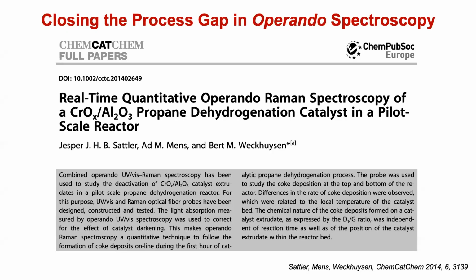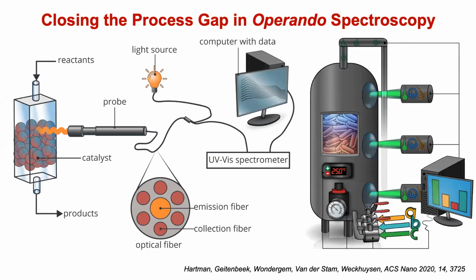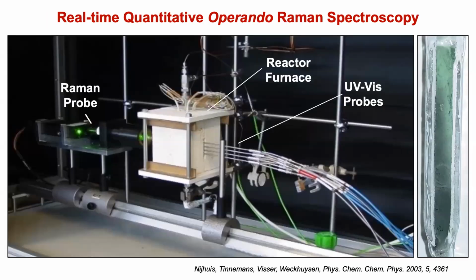This culminated in this paper, actually a ChemCatChem paper, where we published it, but it is a journey. It started first with a praying mantis cell, diffuse reflectance UV-vis, then optical fiber, on the left. And where we want to go is what is shown on the right, where we develop not only temperature sensors and pressure sensors, but sensing devices where you can really measure inside the reactor. It started with taking a reactor, and here you see 4 optical fibers in a row. So you can measure, you have your catalyst bed. So the idea is, can you measure as a function of the bed height?